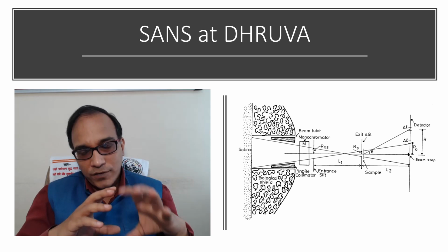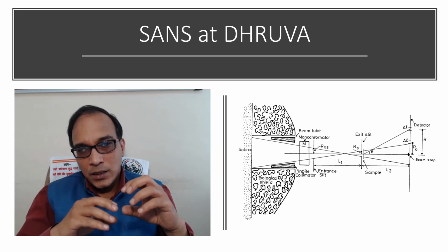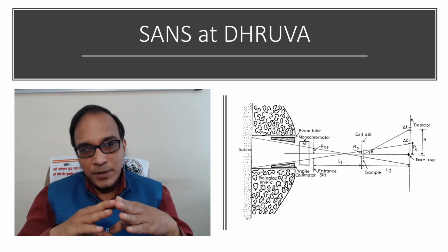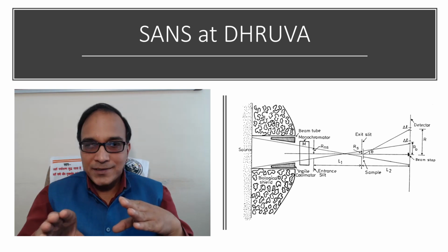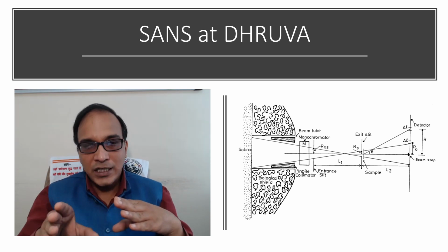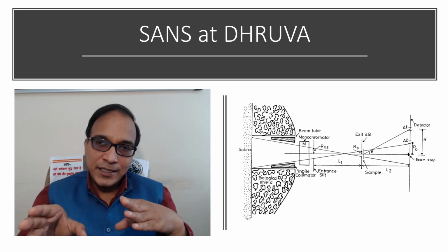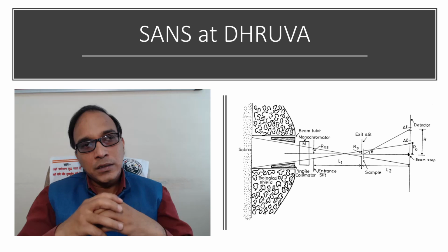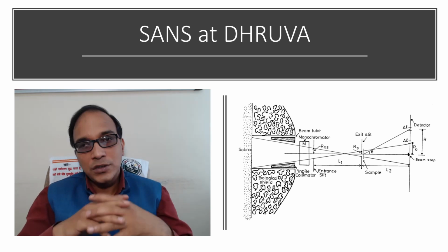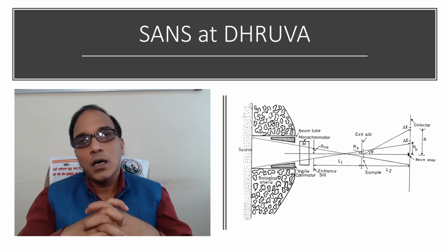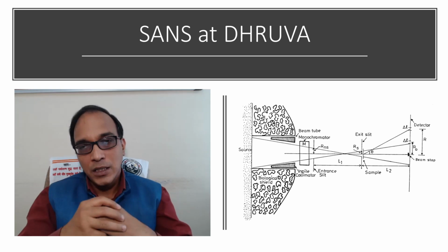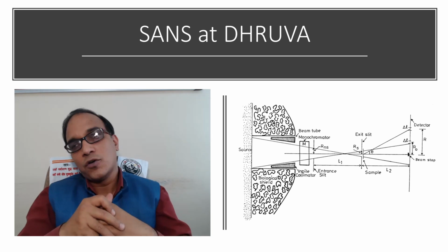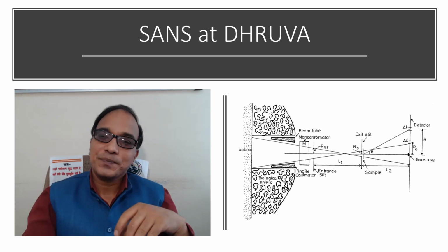After the biological shield of the reactor, monochromators have been placed, and the neutrons are directed to a sample, and through it they are received at a detector. The detector senses the scattering, and this scattering is proportionate to the size and shape, which we can interpret very effectively and very precisely for nanoparticles and these kinds of complexes.